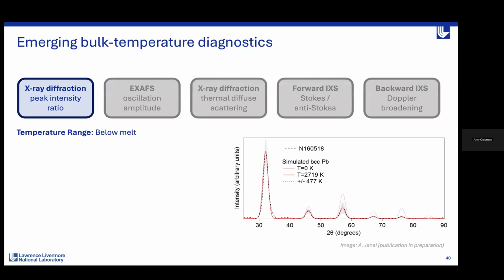Okay, so just to go through these very quickly: if you have diffraction data, temperature increases atomic mean square displacement. So we have these Bragg peaks, and these peaks are reduced by something called the Debye-Waller factor, which affects high angle peaks more than low angle peaks. So if we look at the relative intensity of these peaks in a hot sample versus a cold sample, we can extract a temperature using a Debye model.